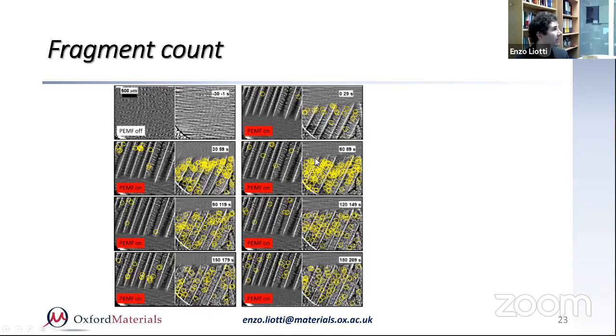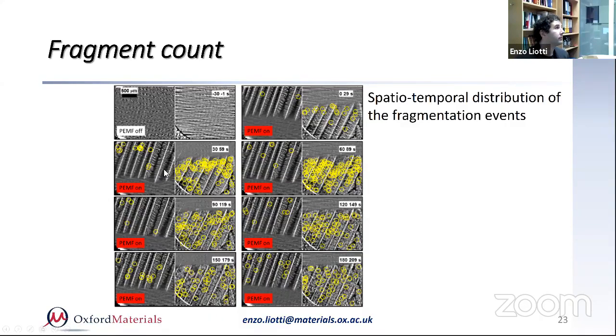And that's actually as time passed. Right, so you should look at it horizontally like that. And you can see that the case at the bottom to top is significantly higher than the other case. In fact, the other interesting thing is that the distribution of